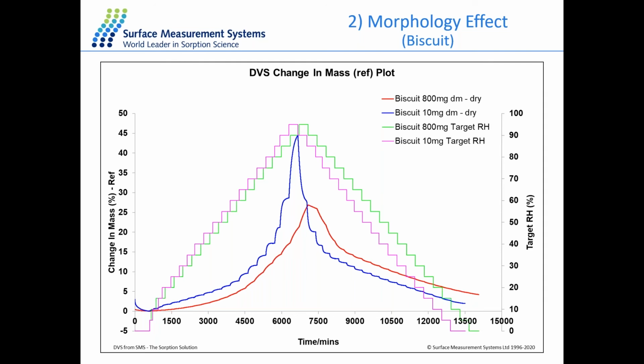So here the blue line is for the 10 milligram sample, and the red line is for the 800 milligram sample. And this time, as you can see, the equilibrium is much better at each humidity step apart from the top stage. And the total uptake for the sample is more than 45% mass change at 95% step in this case. So with the smaller sample mass, we can get a much better quality data with faster sorption kinetics. And that's the result of the biscuit sample.